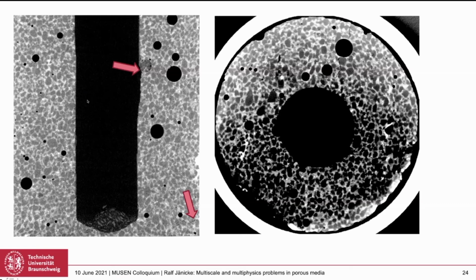And at least we succeeded in a way that we could already now observe at first glance 2 different damage mechanisms. The first one is that this surface was deteriorated, and you see all these pieces here which are falling down. That's something like a microscale damage. And at the same time, we can also observe here a crack, and it's not that easy to see how it continues here. It's really going through the entire wall of this cylinder. And in the top view, we only see that it's not only at the bottom, but it's really going down from the top to the bottom.